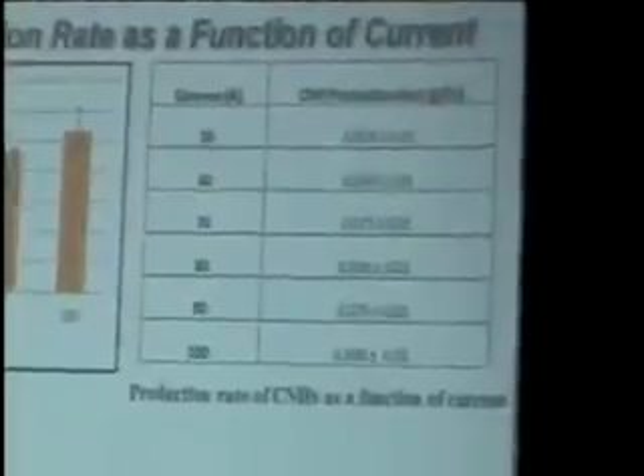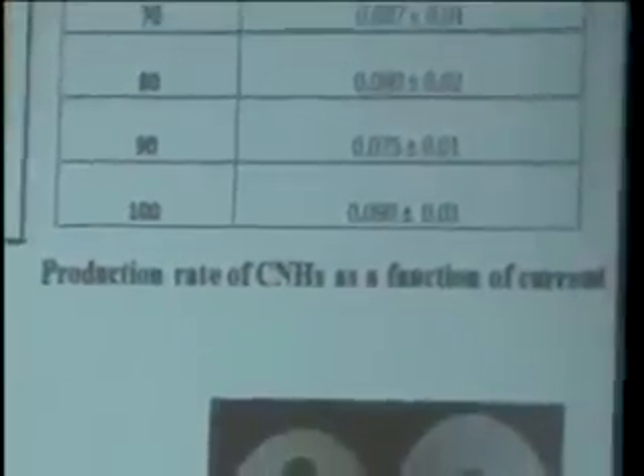This figure shows the effect of different currents on yield. From this figure, one could see that as the current increased from 50 to 70, there was a steady increase in the yield of carbon nanohorns. Beyond that, from 80 to 100, there was no appreciable increase in the yield.